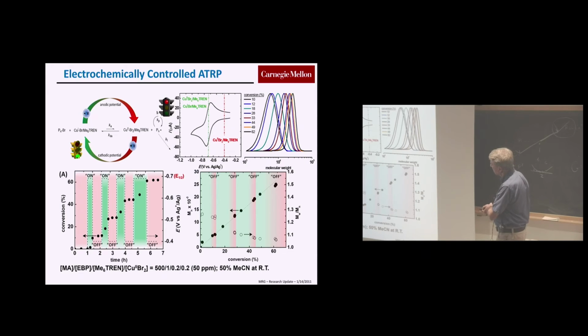So here is an example changing from negative 400 to negative 700 millivolts potential. Negative 400, nothing. 700 starts. I go back to 400, stops, starts, stops. I can climb to whatever conversion I want. And here you could see the molecular weight evolving with conversion, dispersity going to values of 1.05, like in anionic polymerization, if you wish. The entire molar mass distribution shifts to higher values.